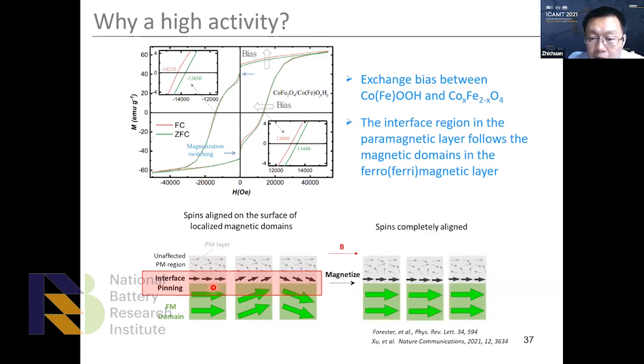So if we apply a magnetic field, they actually will follow, because the magnetic field can manipulate the domain direction of the ferromagnetic material. And the spins at the interface follow the ferromagnetic domain. In this case, they can be indirectly manipulated, right? However, of course, in the region much farther from the interface, they are totally independent, right?